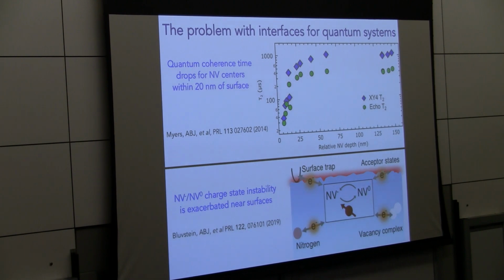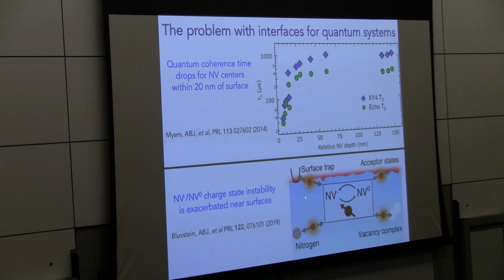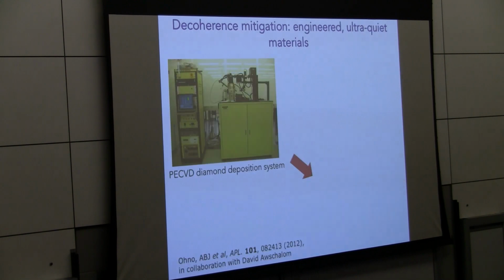So the NV minus that we love, that's the sensor, can give up an electron to surface traps or acceptor states or maybe local defects whose energy levels can be affected by the presence of the surface. And generally, what we found in this recent paper is that we mapped out these charge state instabilities near the surface.